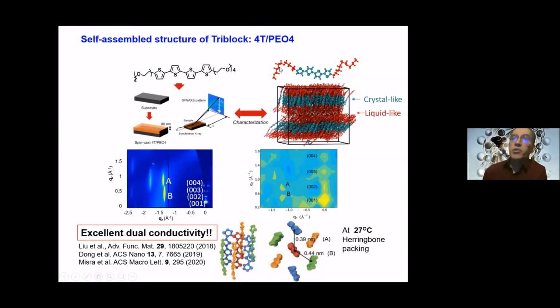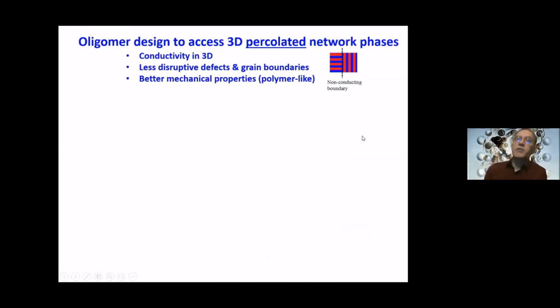One way would be perhaps to explore different lengths of these blocks. But more than that, we wanted to also design 3D percolated network phases, because that would allow us to have conductivity in 3D, not just 2D as a lamellar phase, and also because these network phases are more robust to the disruptive effects of defects or grain boundaries. Like in the lamellar phase, a situation like this will basically kill any conductivity. And finally, as I told you, one reason why people prefer polymers is because they have stronger mechanical properties. Small molecules do not. But if they assemble into these network phases, they will also have very strong mechanical properties. So clearly this will be ideal.